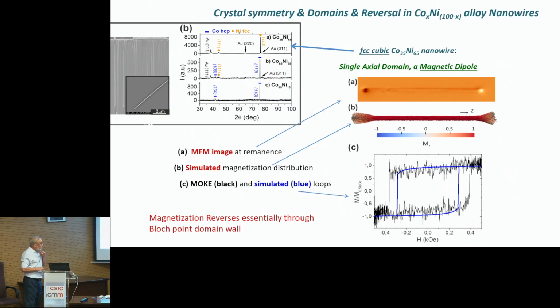So let me summarize for you. The results for this is a cubic cobalt-nickel nanowire with a large content of nickel, so it is cubic. And this is a magnetic force microscopy image. You see this is an ideal magnetic dipole. This black and white contrast indicates that we have a very local distribution of magnetic charges at the ends of the nanowire. And then inside its magnetization is homogeneous.